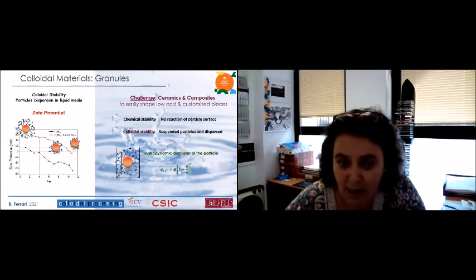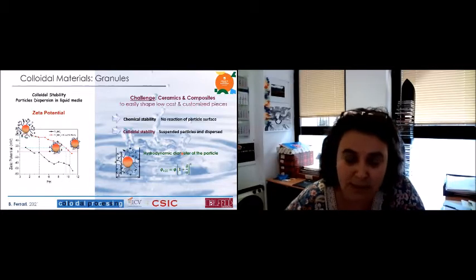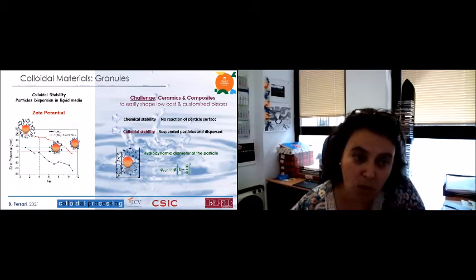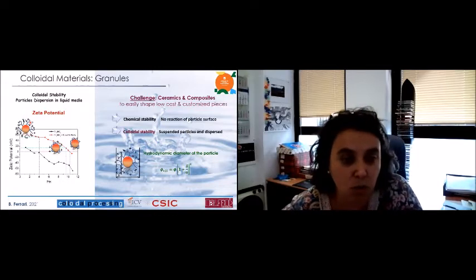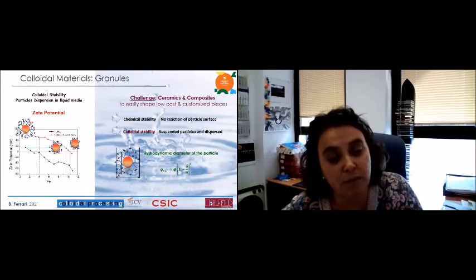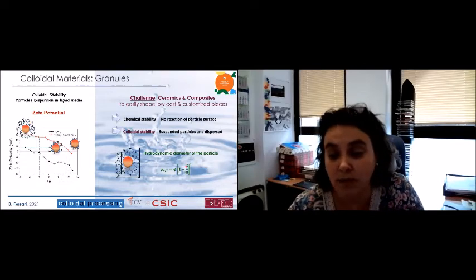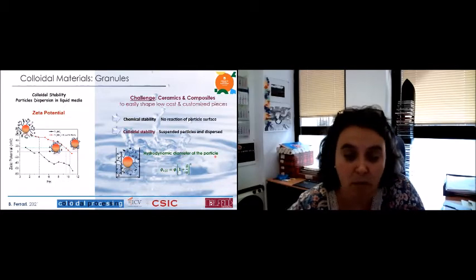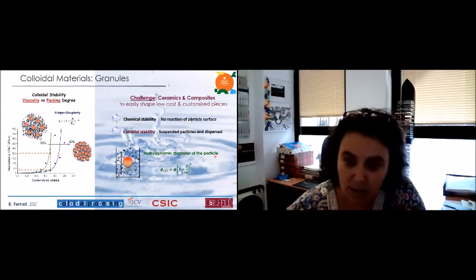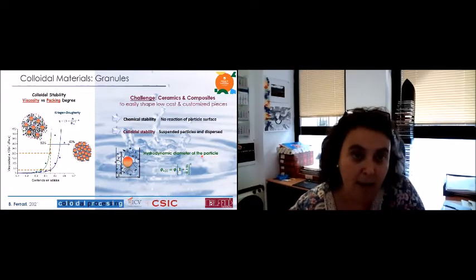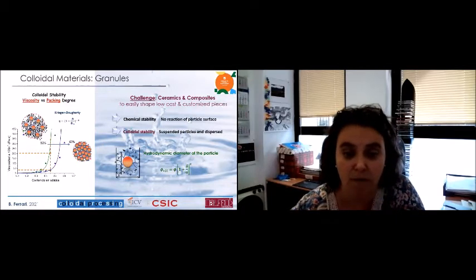And finally, another thing that is very important is to manage the rheology of our particles, trying to promote different kinds of behavior of the polymers that we use to preserve the composition of the particles in water, and to decrease as much as we can the hydrodynamic diameter of our particle and individualize the particle, because our final objective is to have a high packing degree of our particles, right?